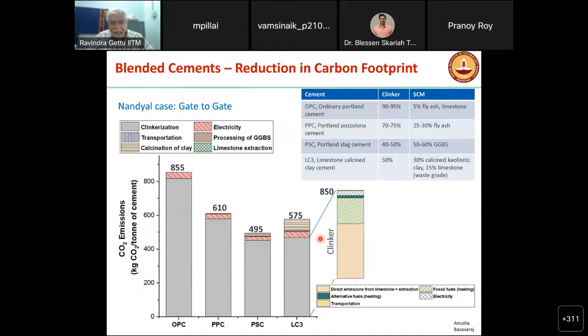LC3 is a new cement that we are working on. This has limestone calcine clay, replacing about 50% of the clinker. So there is a lot of research going on, particularly at IIT Madras. Professor Manu Santhanam, my colleague, is leading this initiative, where 30% calcine kaolinitic clay is mixed with about 15% of limestone powder to substitute the clinker. And this also helps a lot in bringing down the carbon footprint, especially if you don't have fly ash in the vicinity or if you don't have slag. So the starting point has to be a good binder. We have to have a binder that has a low carbon footprint, low embodied energy, available easily to make our textile reinforced concrete.